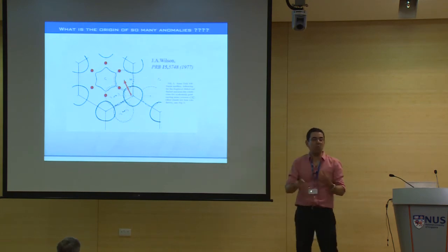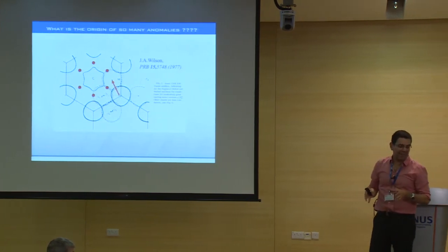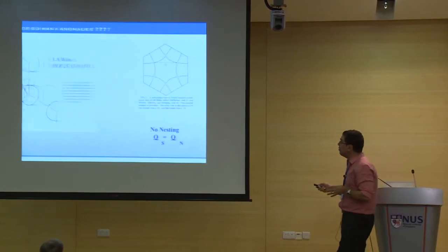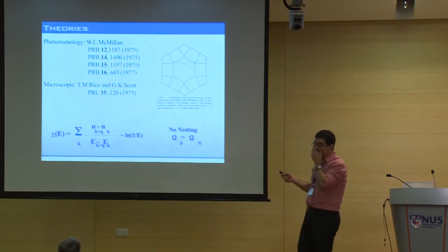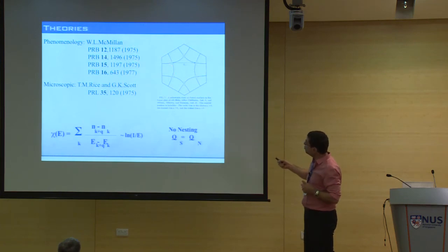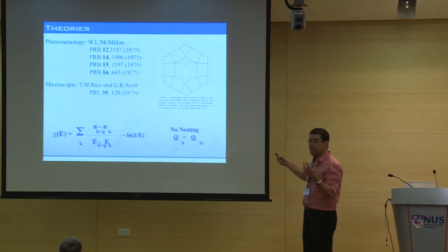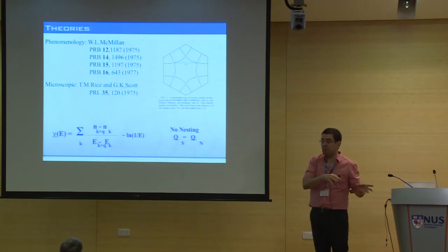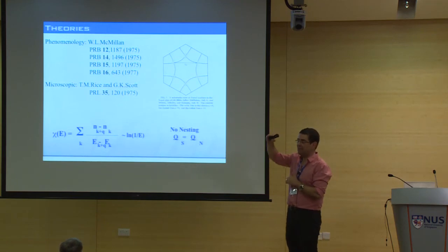Okay? So actually, this was, at the time, considered a good explanation for why you would have something driven by van Hove singularities in these materials. In fact, T.M. Rice, many years ago, when he was a young man, proposed exactly that theory. But the Fermi surface that they drew was very different. You see, this is a Fermi surface of the same material if the Fermi energy would cross these van Hove points. Okay? Clearly different from the previous one, because these van Hove singularities are 60 millivolts above the Fermi level.